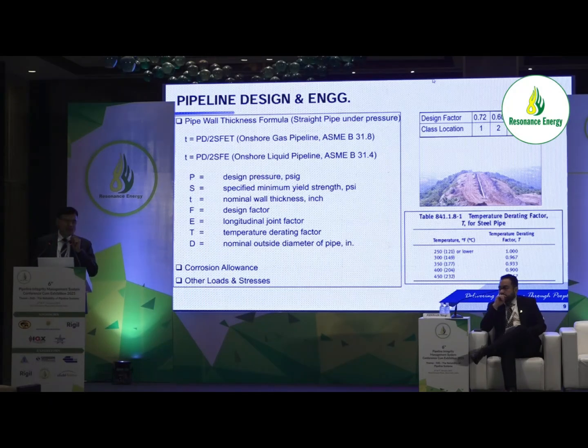Basically, gas is compressible and liquid is incompressible. If there is a leakage in gas, that is a disaster. And gas is operated at high pressure; when temperature goes high, the material strength gets reduced. As per the code, a gas pipeline can be designed up to 232 degrees centigrade, but a liquid pipeline up to 120. Up to 120, as per the code, there is no requirement of temperature derating, but beyond 120 there is a requirement of temperature derating. The temperature derating is for steel. Up to 121 there is no derating, but beyond that there is a derating factor, as material strength gets reduced.